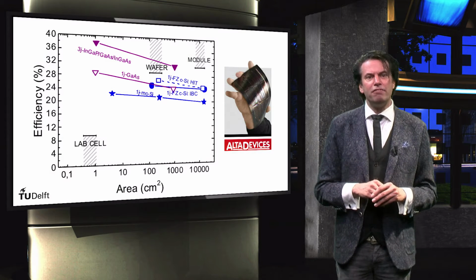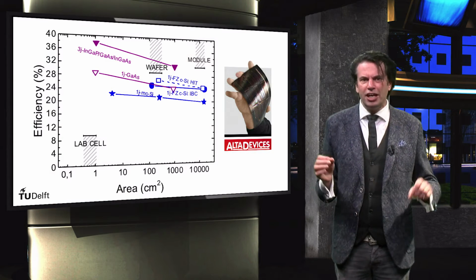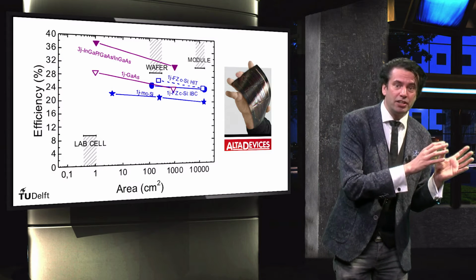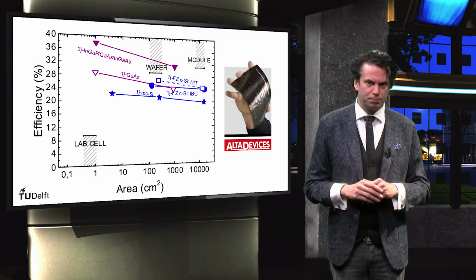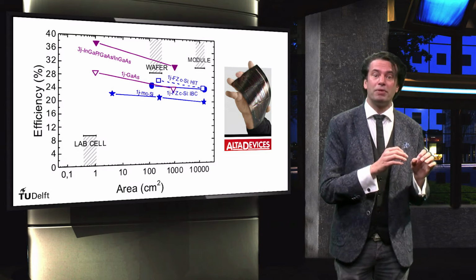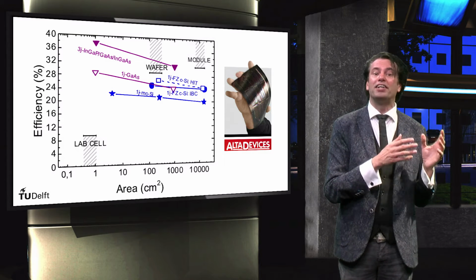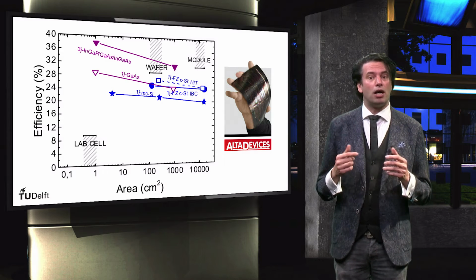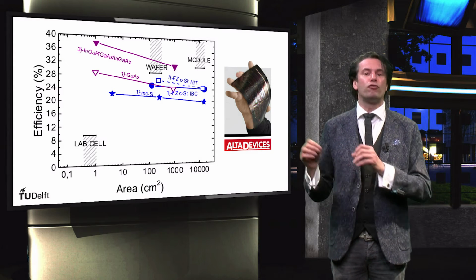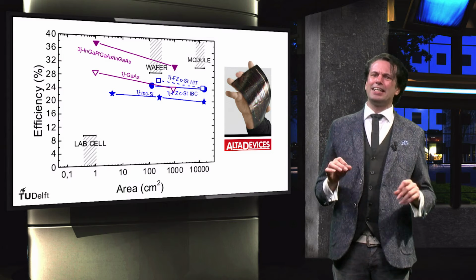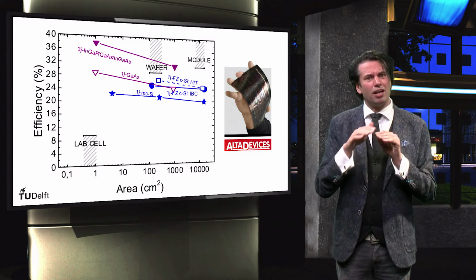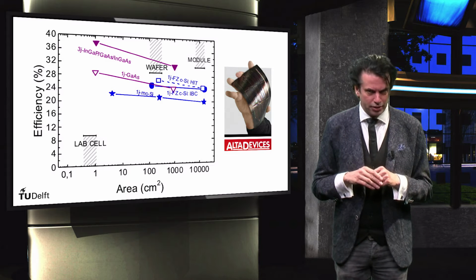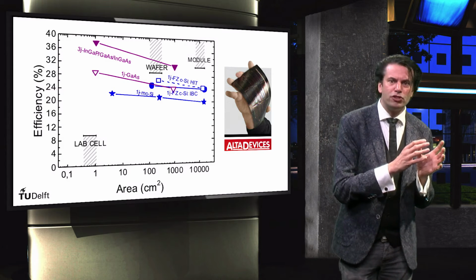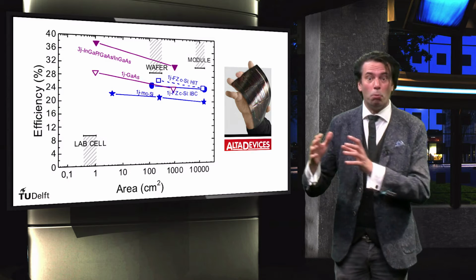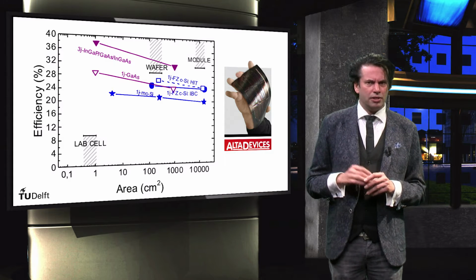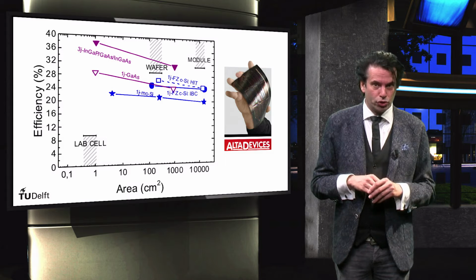Let's consider the 2 PV device structures for the 3-5 PV technology that have resulted in both lab scale devices and small sized modules. These architectures are the thin film gallium arsenide PV modules from Alta Devices and the indium gallium phosphide, gallium arsenide, indium gallium arsenide triple junction from Sharp. It can be clearly seen that the negative slope in this plot is larger than for the crystalline silicon technology. This suggests that upscaling of the single and the triple junction device to module size is more challenging. This results in more efficiency losses.